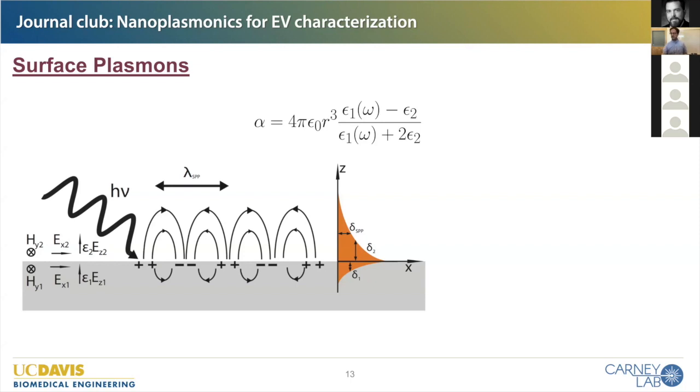So this visualization, even though it's a little advanced, I wanted to show it because it explains why we have the nano part of nano-plasmonic. So why can't bulk gold have this kind of surface plasmon? Well, it's actually not possible to generate surface plasmons by direct coupling of light with smooth bulk metal surfaces, because the propagation constant of the surface plasmon is greater than the incident light wave vector.